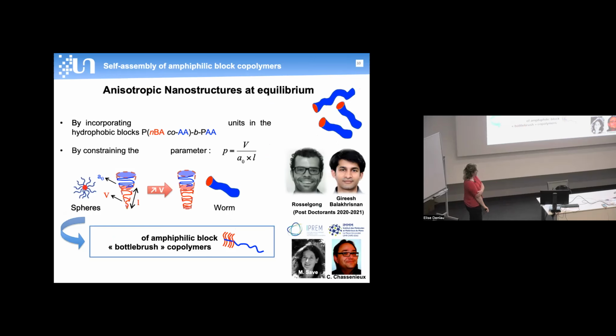So the last work I wanted to show you on the self-assembly of amphiphilic block copolymers is a work that we developed together with Maud Save and Christophe Chassenieux in Le Mans. And this time, we want to target anisotropic nanostructures at equilibrium, so dynamic. And for that, we use a branched structure of the hydrophobic block in order to constrain the packing parameter of the overall polymer chain to a value that is compatible with a flat curvature, inducing worm-like micelles.